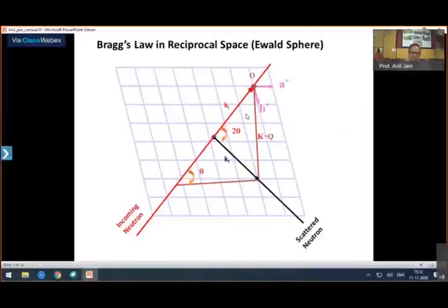So you have theta, 2 theta, omega, which can rotate the sample, chi and phi. By using these 4 circles, you can bring any of these reflections into your horizontal scattering plane, and then you can measure the intensity of every one of these scattering points. Once you have the integrated intensity of all these points, then you can solve the crystal structure.